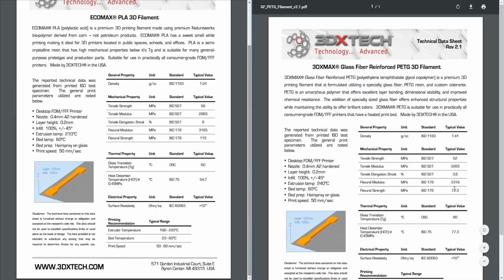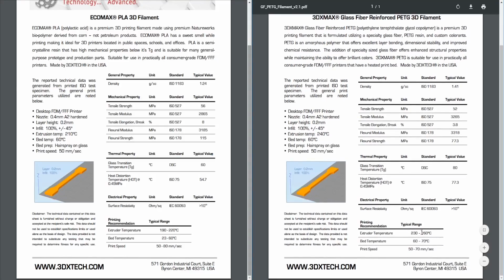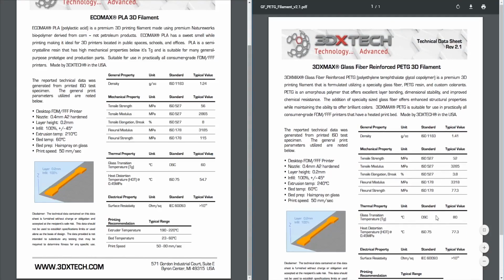Flexural strength 77, and the glass doesn't help it much in flex. It just adds stiffness and a little bit here. But when you pull along with the fibers, it's different from when you're going perpendicular to the fibers. This is parallel to the fibers generally. This is perpendicular to the fibers. It doesn't fare very well. However, this is a low temperature, 230 to 260, so you can print this with the same print as ABS.